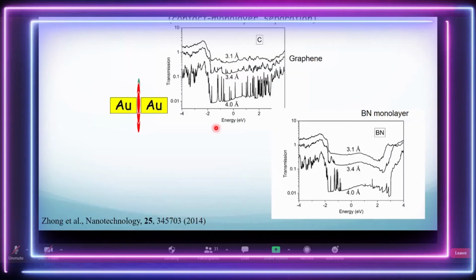So if you go from density of states to the so-called transmission function, the same thing we do here. This is a contact. This is our 2D material. We simply play with the distance between these two. So for the case of graphene, you can see here, this is 3.1, which is our equilibrium separation. There's a large, finite transmission. Now as we separate from 3.1 to 3.4, it reduces. And at 4, which is a weaker bonding with the contact, it becomes small, but we still have these channel states. And this makes sense because graphene is a zero gap material.